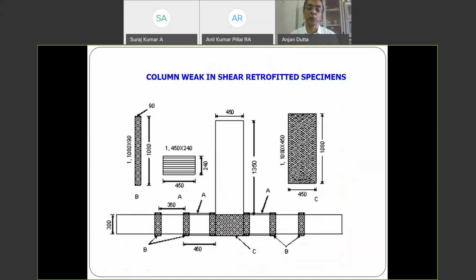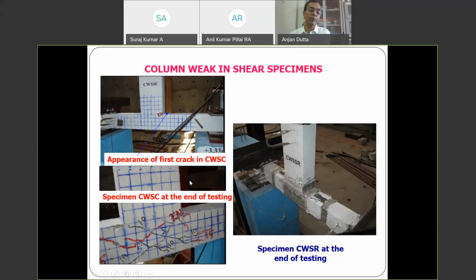Then we have the specimen which is column weak in shear, and you can see that the column has been strengthened using shear reinforcement. These are the failure modes for the control specimen. You can see that in the control specimen after the failure, a lot of failures are taking place in the column, not so much in the beam. And then when we have retrofitted, finally the failures are in the delamination of the strips only.